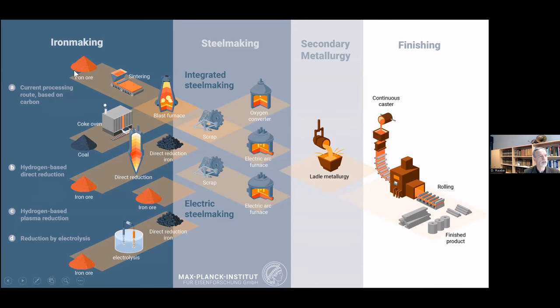You have iron oxides, you go through the sintering of these materials, put them in a blast furnace, go through this oxygen feeding and Boudouard reaction that I mentioned, then you get a eutectic iron-carbon mixture at a relatively low melting point of 1150 degrees centigrade that you tap. And that you put together with cooling scrap in a converter where you extract the carbon with oxygen, and that's what you then call steel and can modify it for your alloy and cast it and so on.